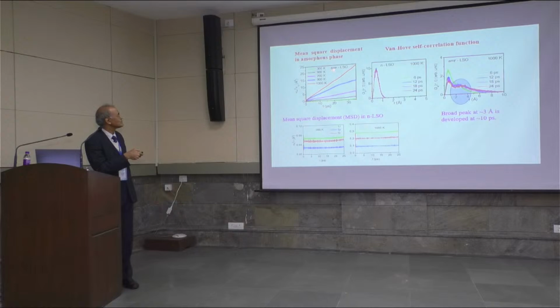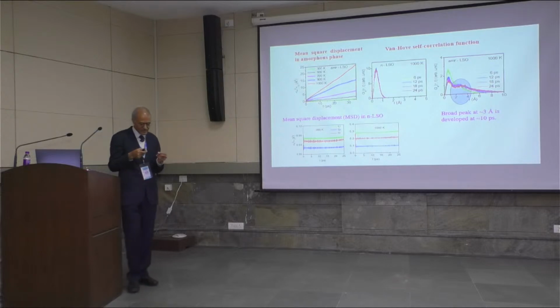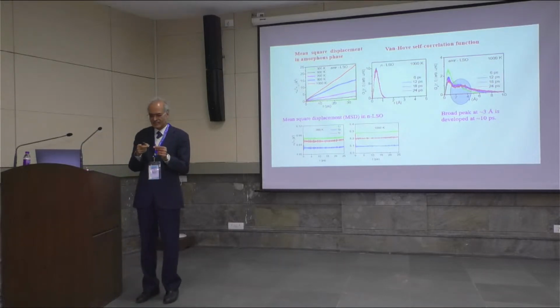Okay, so in this amorphous material, the diffusion coefficient is just proportional to the slope of this function, that is this one. So from that one can identify this. Then another quantity that is calculated is what is called a self-correlation function. It's a correlation function between a lithium atom at a given time and at a future time.